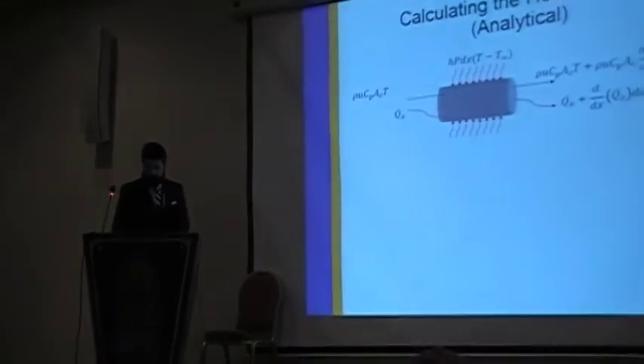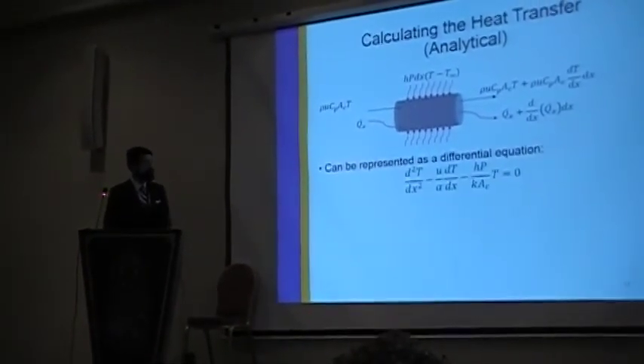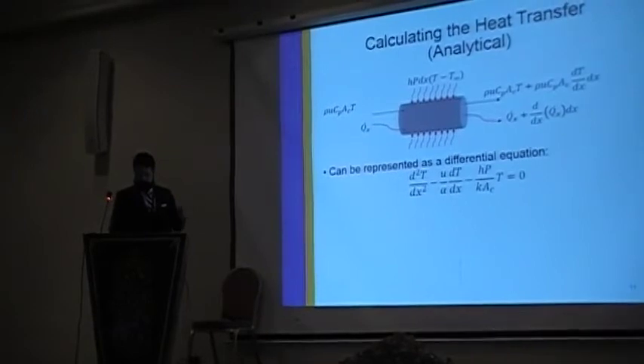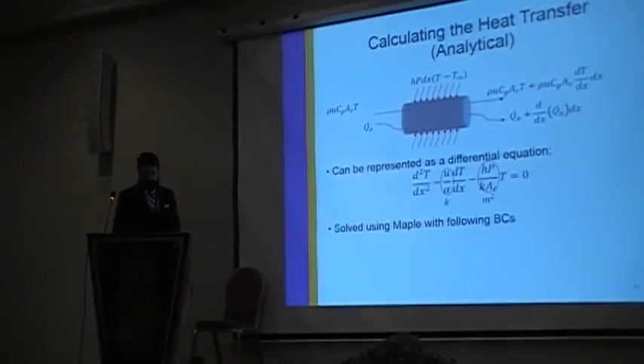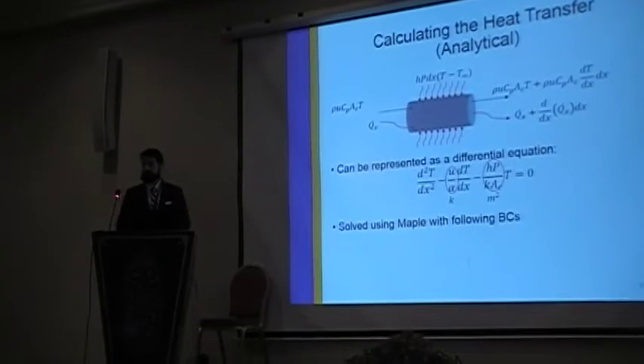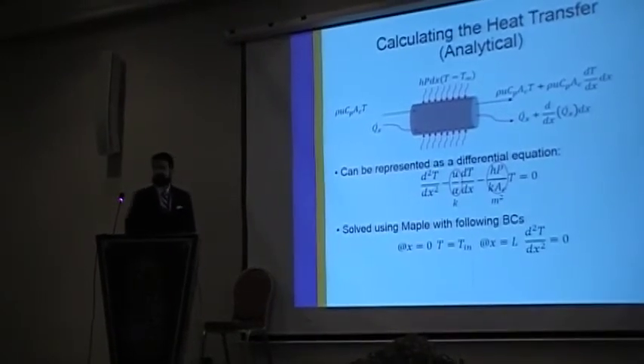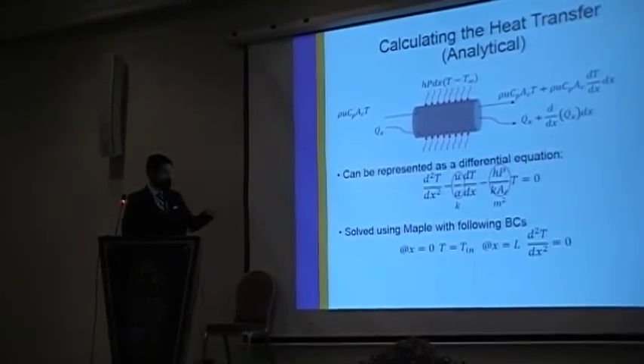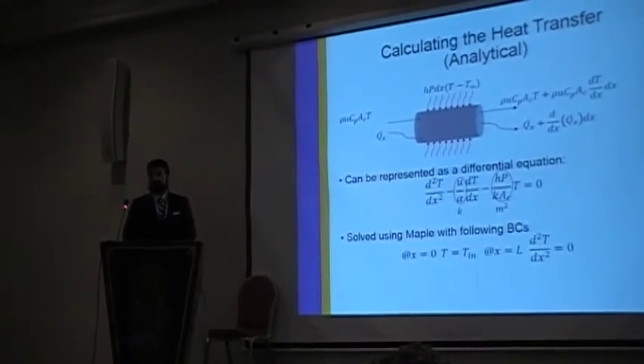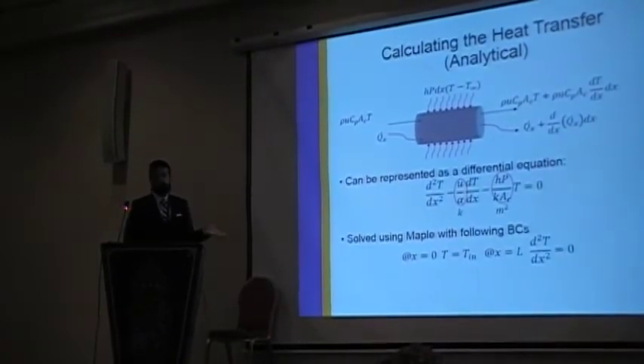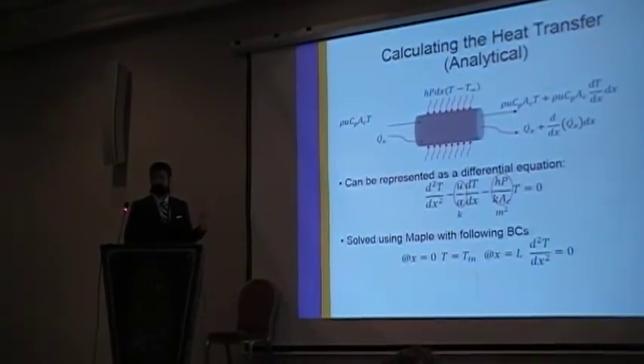Finally, the parameter that we're interested in is the convection, and that H there is the combined coefficient that covers the particle convection, gas convection, and radiation. If we take these, we can represent them as a differential equation, and we can make a simple substitution there for solution. We've solved this using Maple with the following boundary conditions. It's quite tedious to do by hand. What we have is the inlet of the bed is set to the measured inlet temperature, and at the outlet we have the slope of the temperature to be constant.